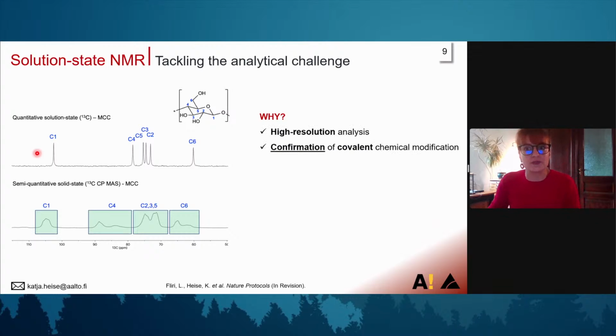And what we can also do is that we can actually confirm covalent modification. And this is very often the case with solid state NMR, is that you modify your cellulose, but you cannot really distinguish in many cases between surface adsorption of a compound and real covalent modification. And this is something, I will show you the technique for it in a few minutes. This is something we can do with solution state NMR, of course.